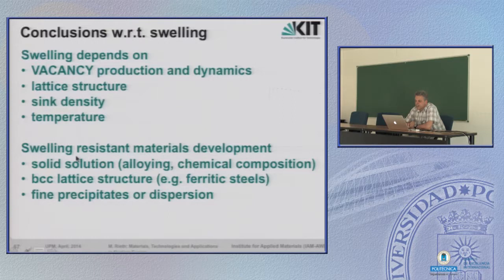Swelling-resistant materials are based on solid solution. Alloying chemical composition is an important measure to avoid or reduce swelling. And the BCC lattice structure, for example in ferritic steels, is at least in steels better compared to the austenitic steels. And fine precipitates or dispersions help also.